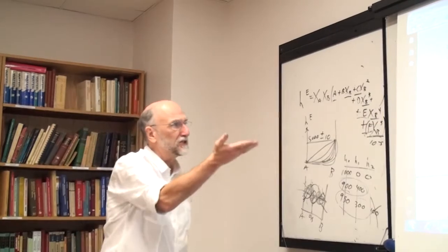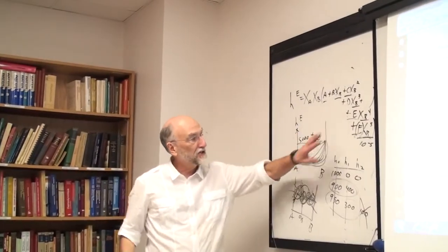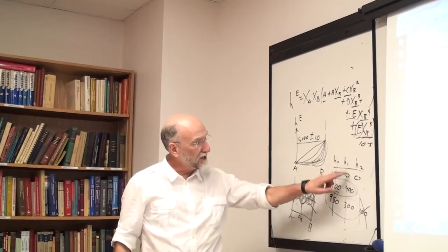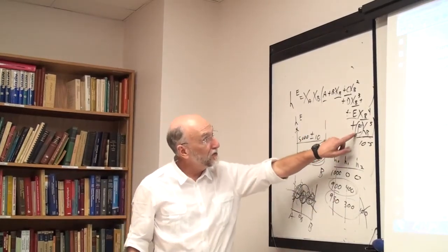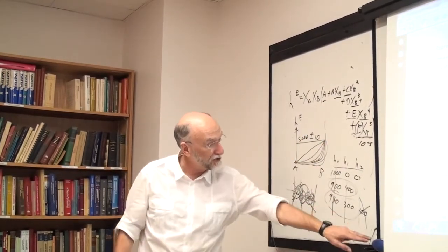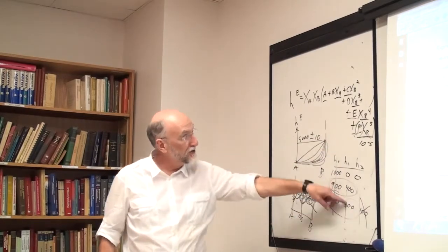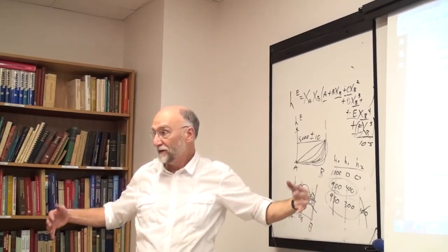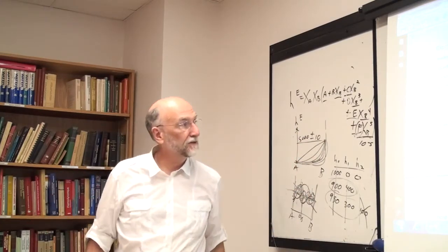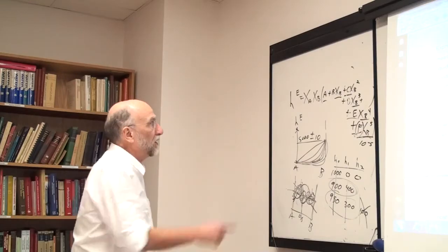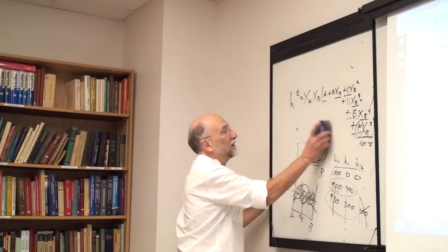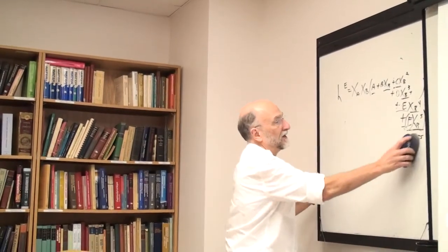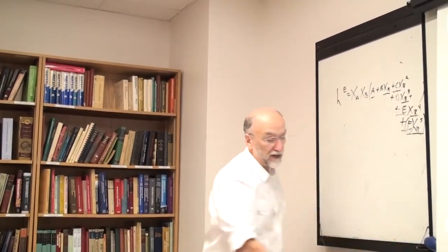But remember, the 2 equations are exactly identical. You can take the Redlich-Kister terms and convert them into this, or vice versa. But if you take a Redlich-Kister expansion of 7 terms and do this conversion, you'll find that these terms here are getting bigger and bigger and bigger, with varying signs and so on. Why would you then ever want to use the regular power series? You might want to use it when this is in fact the form of the function you're trying to fit.